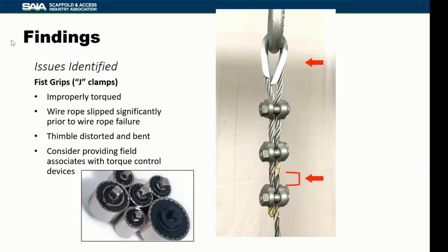One of the things that has been recommended to me is that there are special adapters that can be used with a standard socket. It doesn't have to be a torque wrench, but these are special torque adapters that can be preset to a specific torque, and then they will click much like a torque wrench. And these can be used with standard types of ratchets and sockets. That might be a piece of equipment that you would want every technician or every mechanic to have in the field when they are installing fist grips, so that they know specifically that they had achieved the 35 foot-pounds of torque that are required for fist grips to perform adequately.